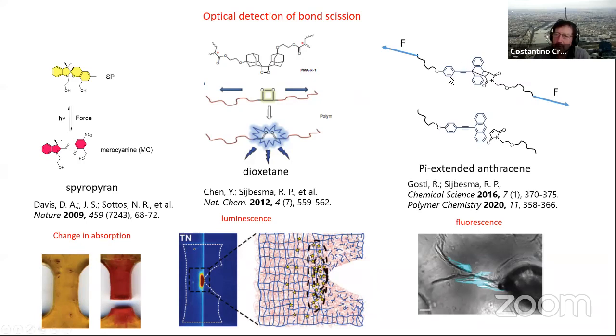So this version with the pi extension, this fragment here is fluorescent. If you look at the intact molecule, it has a bond, called a Diels-Alder bond here. This intact molecule is transparent, so it doesn't absorb in the visible range and also does not produce any fluorescence if you illuminate it. But if this bond breaks, and this is a bond that is a bit weaker than a covalent bond, but it's still a strong bond, and this fragment here becomes fluorescent. So one of the two fragments can then be detected. Now you will see that it has some advantage.